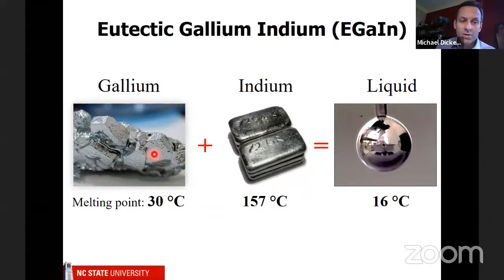So this is a crystal of gallium. And we want to make sure that it's liquid at room temperature. So to do that, we add other metals like indium. And this is one of the interesting things about nature. When you mix together two materials, you end up with something that's got a lower melting point. And we choose the composition that gives us the lowest melting point, which is about 15 or 16 degrees. And that's called the eutectic.